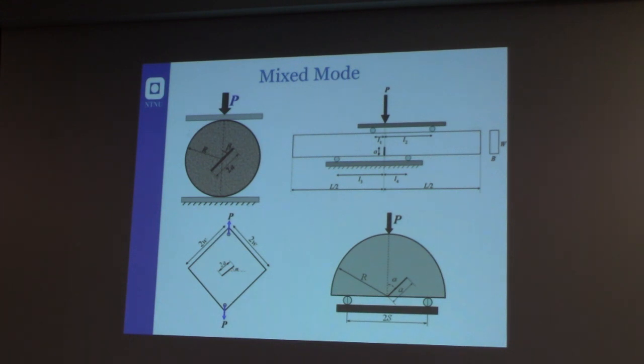But actually, I think one of the most critical problems that we have in a fracture mechanics problem is that usually it's very difficult to have a component subject only to mode 1. So usually you have a configuration with a kind of mixed mode loading combination. You have cracks that are inclined with respect to the direction of the load, and so the local stress field is not mode 1, but a combination of usually mode 1 and mode 2. And if you also have out-of-plane loading, it's also a combination with mode 3.